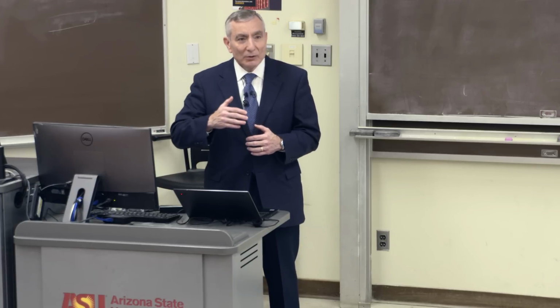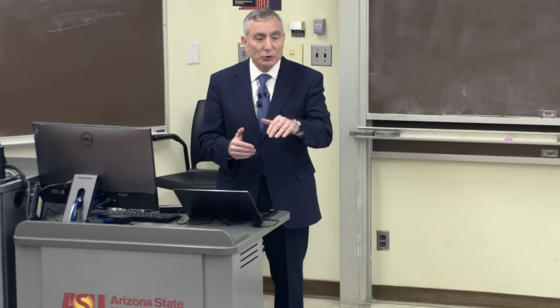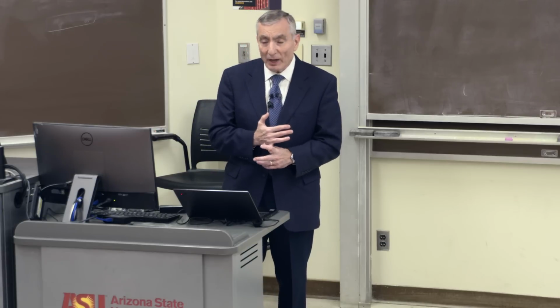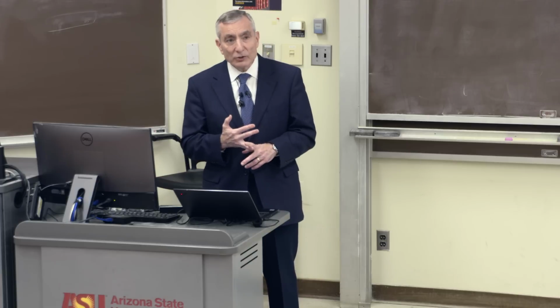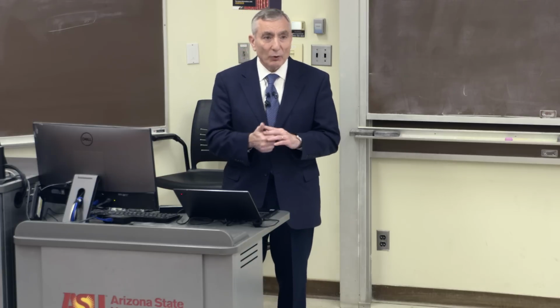And now flash it quickly at 1200. That's enough to get the sulfur atoms to insert and have plenty of sulfur there. So we call it reflashed, sort of like refried beans. I mean, you flash it, and then you flash it again at a lower temperature, because you don't have to make graphene anymore. You just have to hit a temperature where you can do the insertion. And that's what we found works very well with boron, nitrogen, oxygen, sulfur, and fluorine.